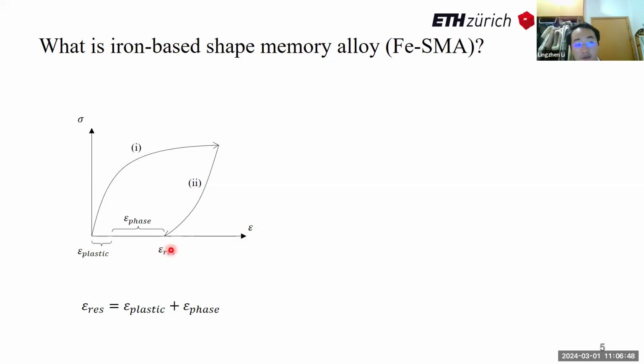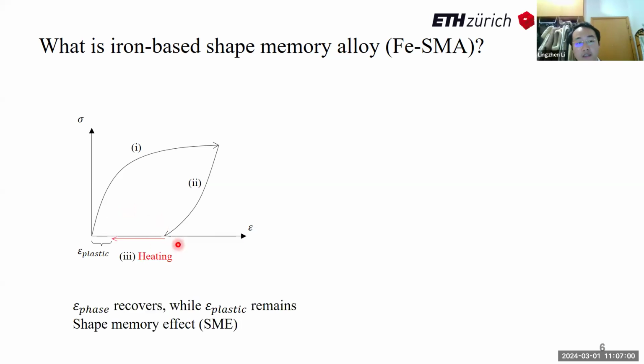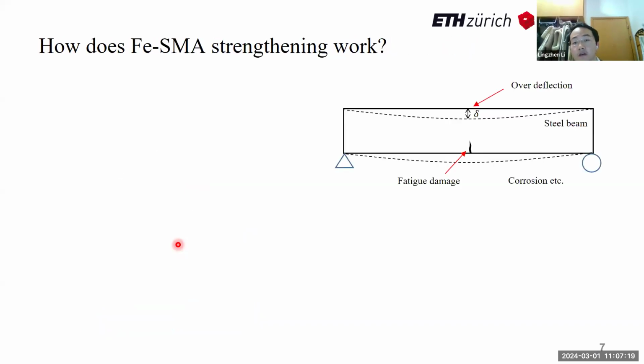For traditional steel material like mild steel or high-strength steel, this is the end of the behavior. But for our shape memory alloy, this phase transformation strain can be fully recovered by heating to a certain temperature. And this phenomenon is called the shape memory effect, as if it remembers its original shape. And we can use this special property, shrinking during heating, for prestressed strengthening. Here is a schematic example.